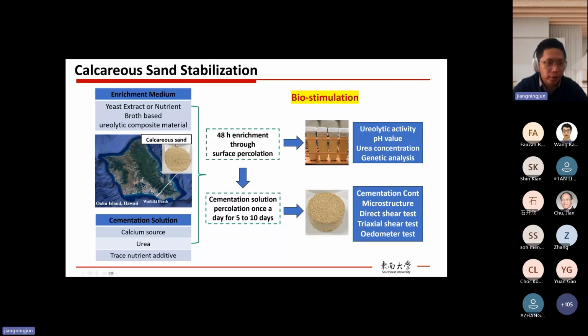In this particular research, we used the biostimulation approach because we think it's more eco-friendly. We first prepared the enrichment medium consisting of either yeast extract or nutrient broth plus some urea and other materials. Then we prepared the cementation solution consisting of calcium, urea, and some trace nutrient additive. First, there was a 48-hour enrichment through surface percolation, so we can complete the stimulation process. Then we took some soil samples and extracted the pore solution for analysis such as ureolytic activity, pH value, urea concentration, and genetic analysis.